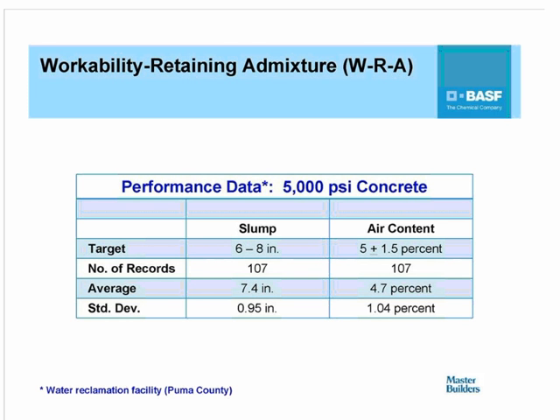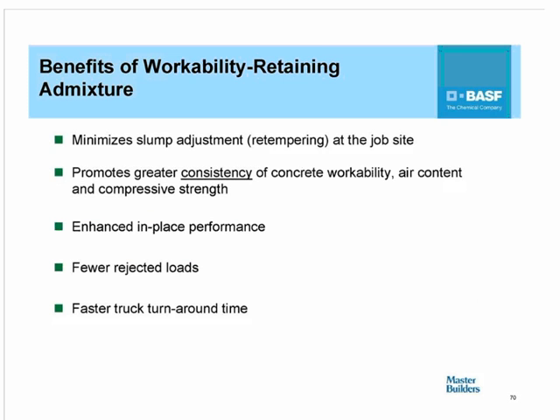This was a project where the specified compressive strength was 5,000 psi, but more importantly, the target slump was 6 to 8 inches, and the target air content was 5 plus or minus 1.5%. And the average of 107 records was an average slump of 7.4 inches and an air content of 4.7%. Needless to say, the contractor on this project was extremely pleased with the performance of the concrete, as was the